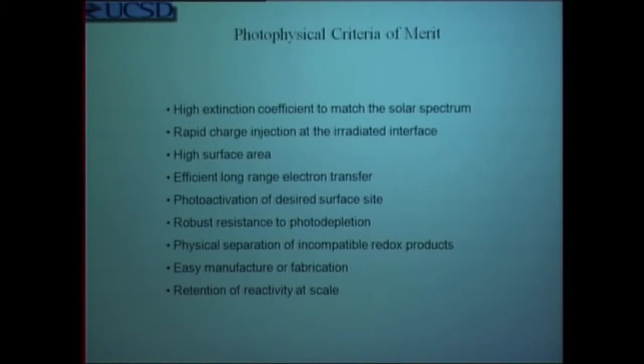You need to have a material that has rapid charge injection at the irradiated interface. The bands have to bend enough so that they move apart rather than recombining very quickly. You have to have a high surface area because otherwise you won't have enough highly absorptive material at the site where the photon comes in. You need to have efficient long-range electron transfer, and by that I mean that the charges, whether positive or negative, are trapped by a reagent. And that leads to the consequences that I showed you.